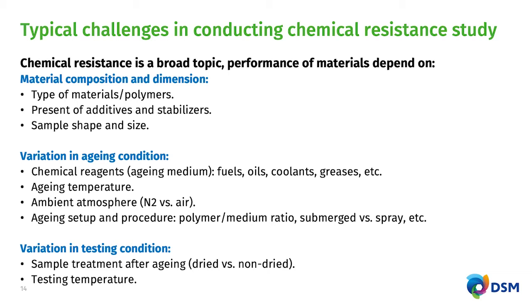As you can imagine, different materials or different polymers will have different resistance. Sample shape and sample size also play roles. So thinner tensile bars, for example, will be degraded much faster than thicker tensile bars. So design criteria for thickness is also very important in this case, because we need to make sure that we age the more representative samples during this type of study.